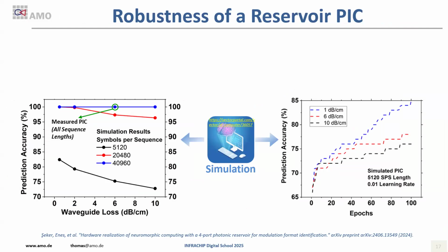We also looked at this: we cannot vary the losses of the chip as we wish. We can only hope to get the best loss when we fabricate something. It's just accidental that we got a 6 dB per cm loss, which is high loss, but all the other chips that we later measured were even better than that. But by simulation, we tried to sweep the loss parameter and see how the accuracy goes. You can see up to 10 dB per cm, which is a very lossy chip, even then, for certain scenarios, it is still within 95%.